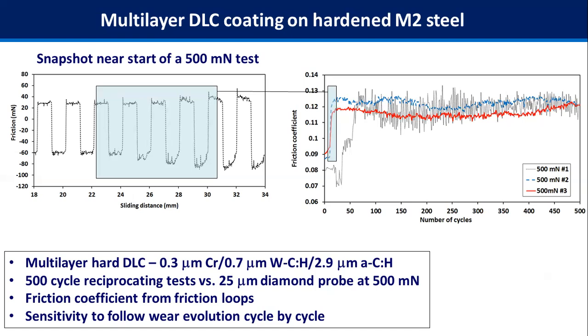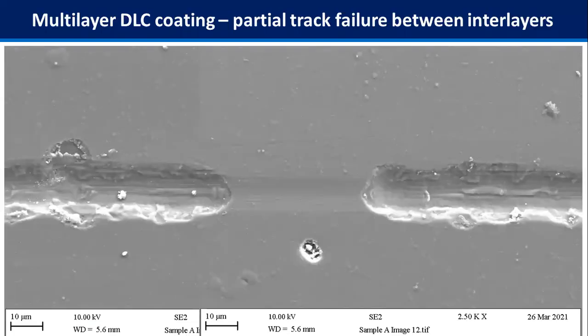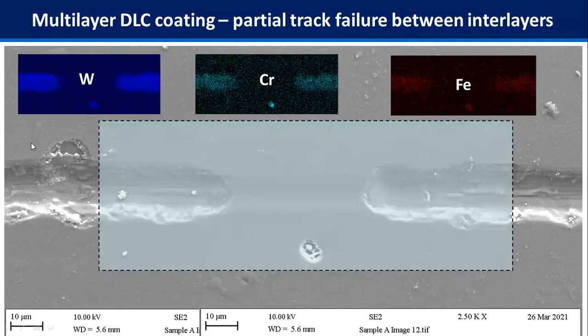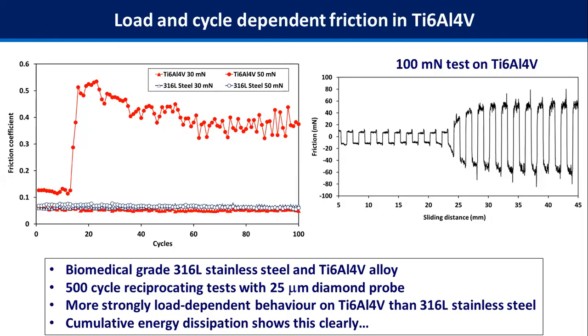If we look at the other test, we can see actually something slightly different is happening. It's a much more jagged frictional response. So we looked in more detail with SEM, and we can see here that there's a sort of partial failure, fracture of the scratch track. So in some regions, like in the center here, it's just a normal wear track, but here you're getting a transition to a more fractured zone. So if we do EDX, we can see there's a lot more tungsten in this, a little bit of chromium, and maybe a little bit of iron. So this is a fracture within the coating system. So this is all very useful information for coating designers.